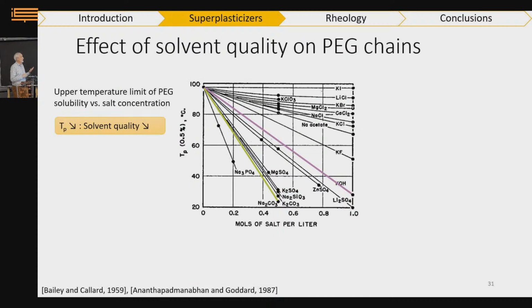One measurement that is well known in the literature is to look at the temperature of precipitation, TP, for a polymer. Here it's a PEG, which is relevant because our side chains are PEG. And what you see here is that as you increase the salt concentration, the precipitation temperature drops, which means that the quality of the solvent drops. The polymer becomes less and less soluble. So it's still soluble, but it's less happy, let's say. Okay, so it's not a phase separation. It's important. It's not a precipitation. Here is a precipitation temperature, but it tells us what's going on right before the precipitation.